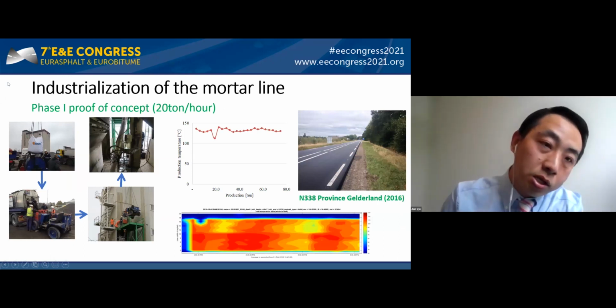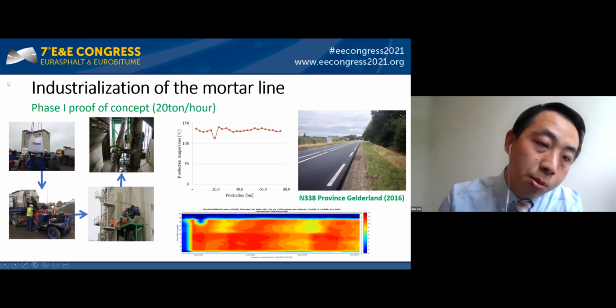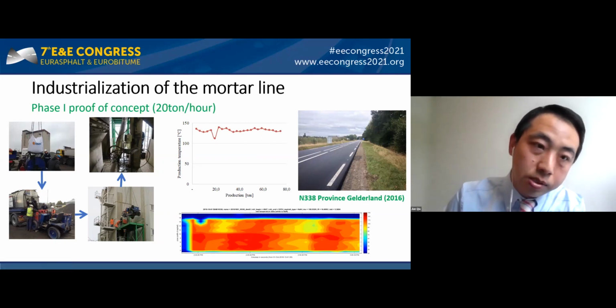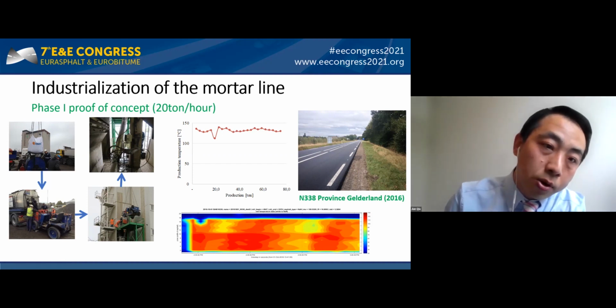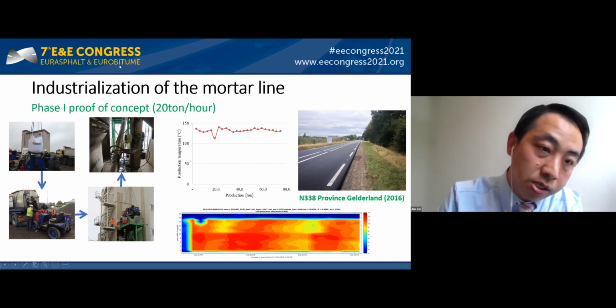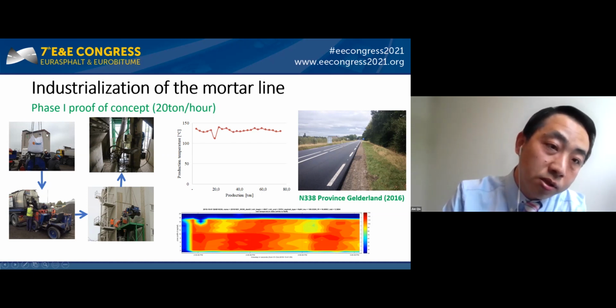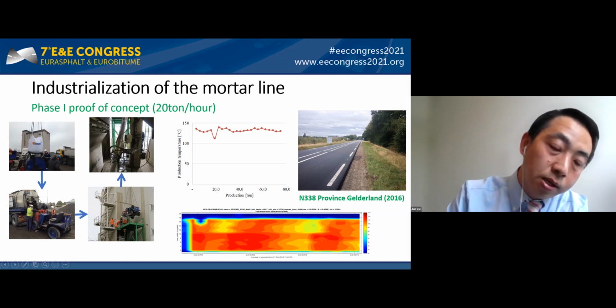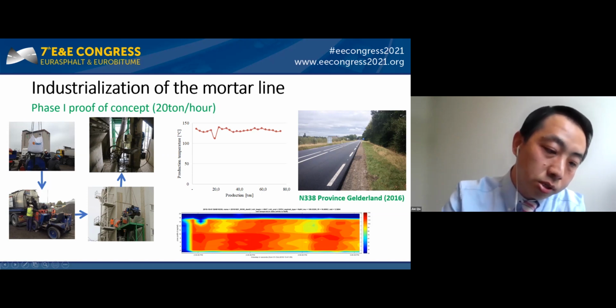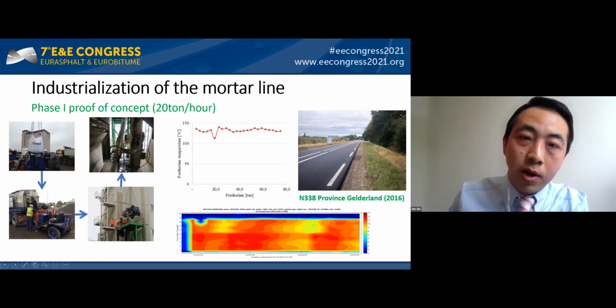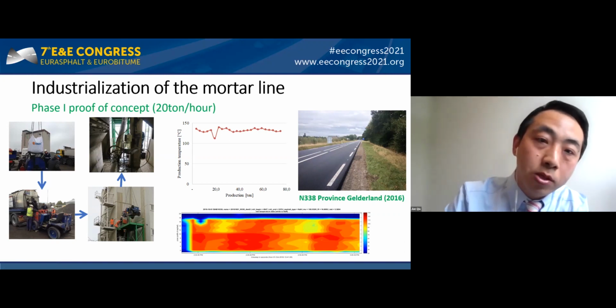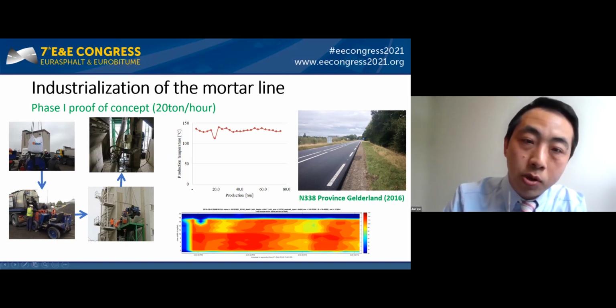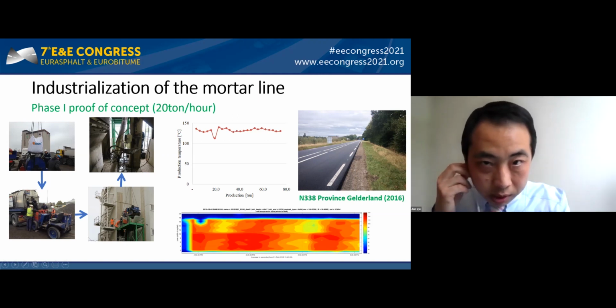There is no standard mortar dosing for a mortar production unit. The only thing is you can borrow it from the mastic asphalt. We did it first with the mastic asphalt concept. We use the steering cable from the hot asphalt, and we dose the mortar in, and also the softer bitumen. Afterwards we use a dumper to lift it into the side of the plant, and by making a dosing pipe out of it, we are now able to dose the mortar into the mixer.